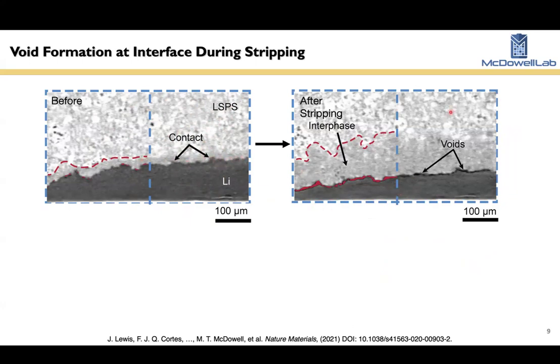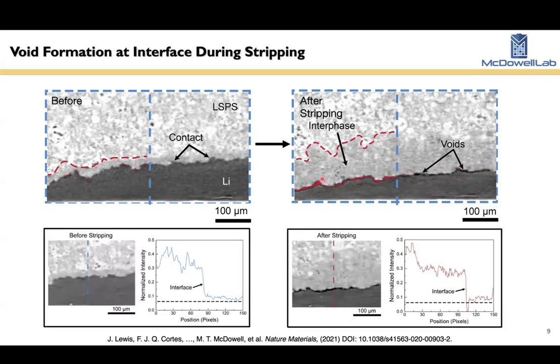After we've oxidized and stripped lithium, the lithium electrode has shrunk a lot. It's decreased in thickness, but also you form these dark splotches at the interface. These are voids. We know these are voids because their intensity is lower than anywhere else in the cell. It's just a lack of material. And we can map out these voids by doing image segmentation across the entire 3D structure of the cell and classifying different voxels into different phases based on their intensity and proximity and other factors. Here we see that the interface intensity is very low when the voids form.